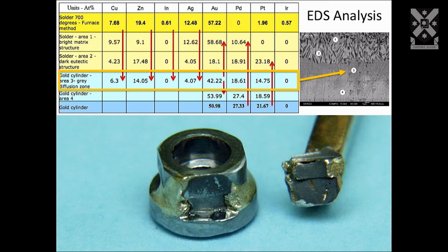And this was confirmed when we did the elemental analysis using EDS. And what we were finding was that when the solder was soldered to the bar, which was a type 4 gold alloy, they contained similar elements and there was equilibrium. There was no movement. But when it was soldered to the non-oxidizing gold cylinder, platinum and palladium are very reactive, especially at temperature. And the gold, platinum, palladium was migrating out, diffusing out into the solder, and copper, zinc, and silver was migrating inwards, forming this gray zone. And this was this brittle zone that we were inadvertently creating.